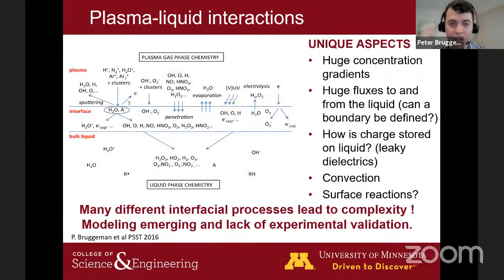Now, what is so much more challenging there? Of course, you have the same kind of species fluxes, but the key difference is that water can evaporate, so you can have a huge amount of liquid phase species that get into the plasma and really change your plasma. So you have this very strong coupling between plasma and liquid. But water behaves quite differently, from a fundamental point of view, of charged species going to the liquid, how charges are stored. Solvated electrons would be penetrating, whereas on dielectric solids, electrons would be only on the surface. So there are a lot of differences in how the interactions between a liquid and a plasma would work.